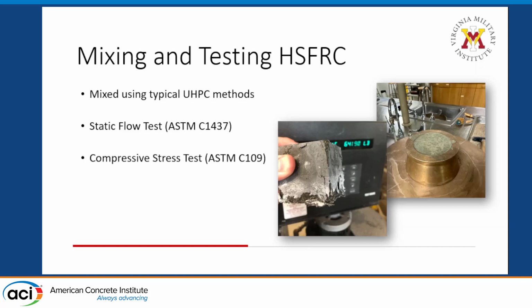And the results from the static flow test showed that the quartz sand mix flowed about 16.4 centimeters and had the smallest flow, and the Fuller mix had 22.65 centimeters of flow from the static flow test and had the largest flow, and all the other mixes had ranges in between there. So for this project, they were considered acceptable, and the main test with this project was the compressive stress test